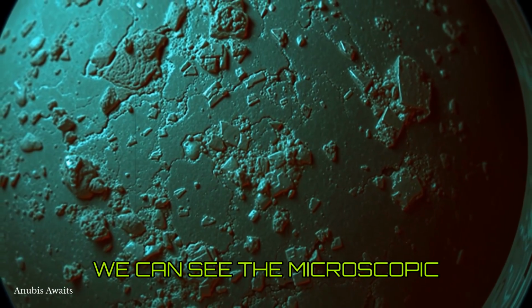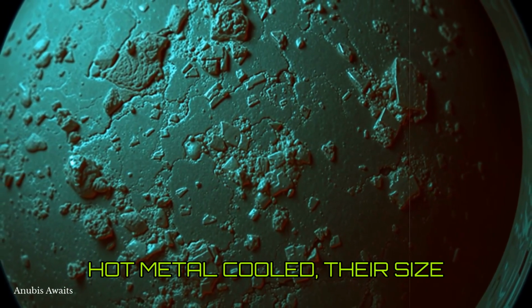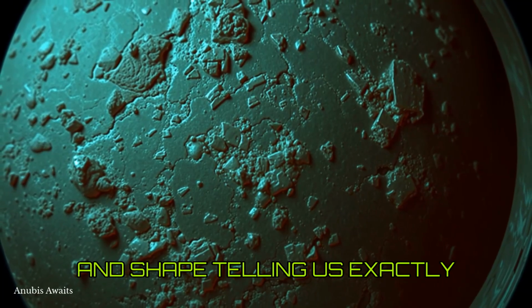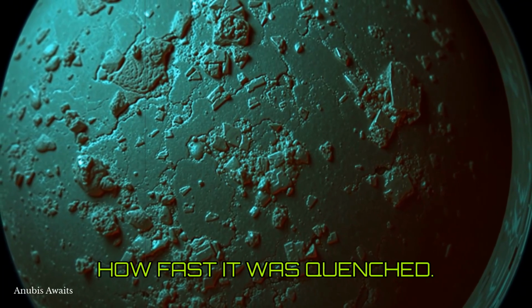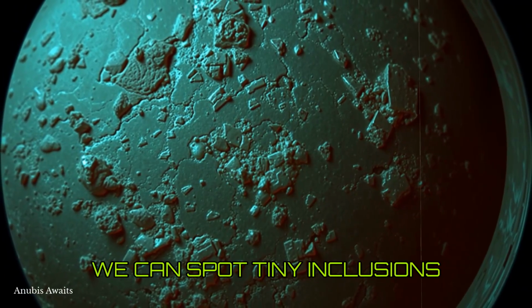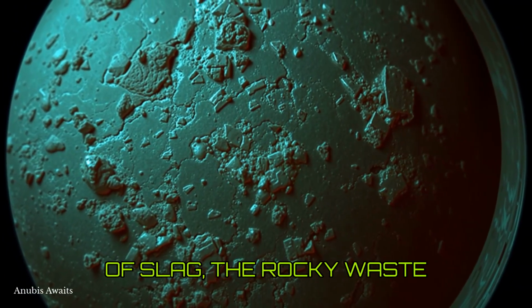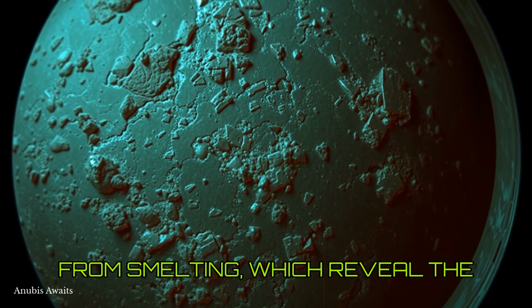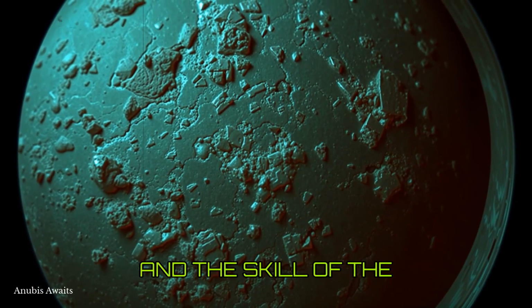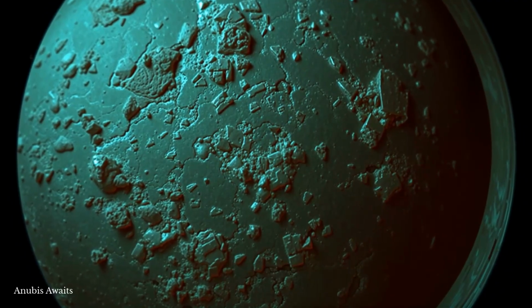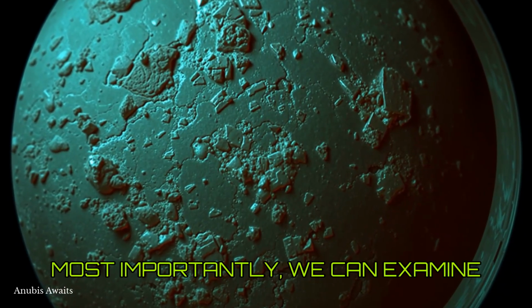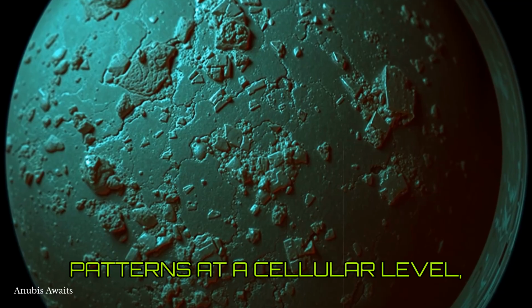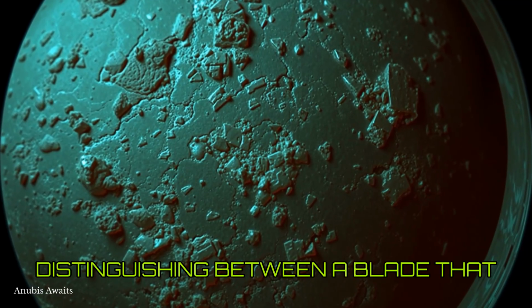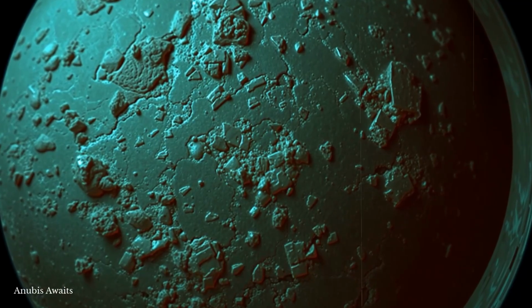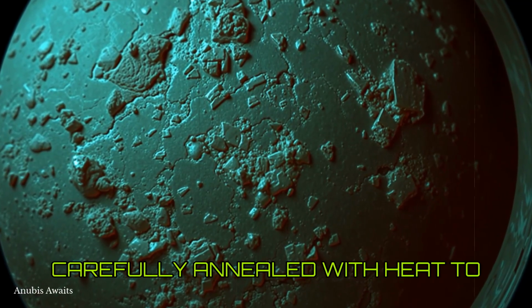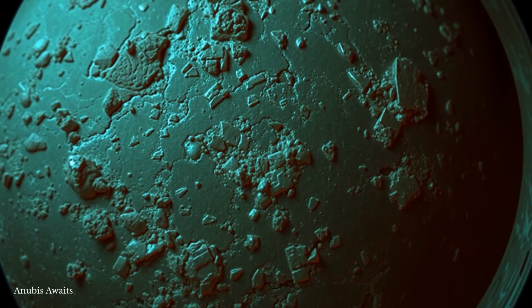We can see the microscopic crystals that formed as the hot metal cooled, their size and shape telling us exactly how fast it was quenched. We can spot tiny inclusions of slag, the rocky waste from smelting, which reveal the quality of the original ore and the skill of the furnace master. Most importantly, we can examine the tool marks and wear patterns at a cellular level, distinguishing between a blade that was cast in a mold, hammered on an anvil, or carefully annealed with heat to remove stresses.